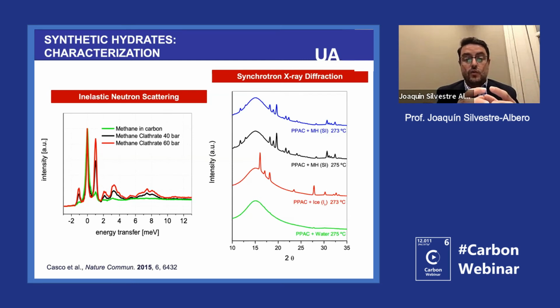However, when you have isolated methane molecules, they can rotate freely, and then you have a huge peak. And this is what we were observing, for instance, in the red. That was water plus methane at 60 bars. And you can see that you have a very beautiful peak at 1 millielectron volts. And this is showing that you have isolated methane molecules rotating. So this is a confirmation that methane is trapped in the cavities of these gas hydrates.